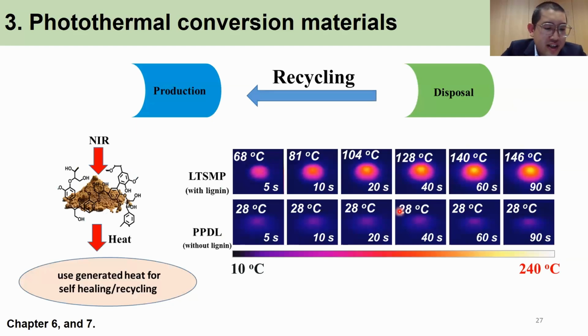The third application is the photothermal conversion material. Lignin is a natural photothermal conversion particle, it can convert light into heat in just 90 seconds. The surface temperature can reach 146 degrees. This temperature is enough for the material repair or even for the recycling.